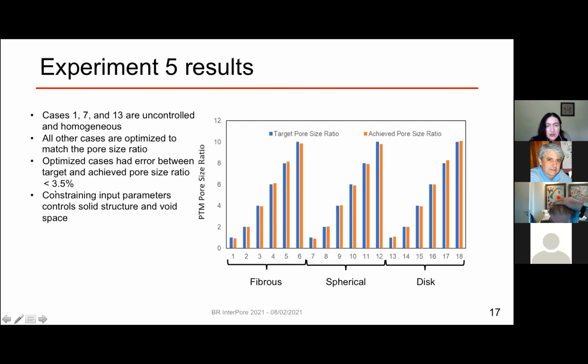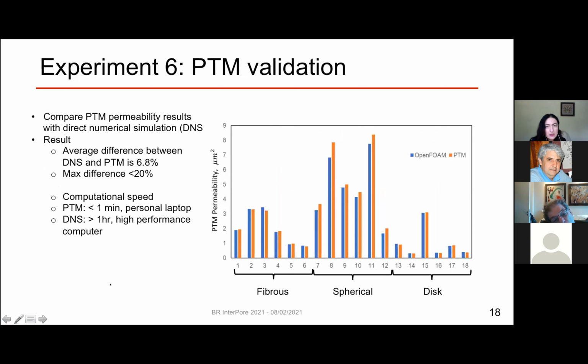So what we find is that constraining input parameters helps us control both the solid structure and the void space, and the error between what we wanted to achieve and what we achieved is under 3.5%. So we're happy with that also. And our sixth and final experiment, we wanted to see how well does the pore topology method perform. That is the one that computes all of these material properties, whether it's porosity, pore sizes, or permeability, compared to direct numerical simulation. And we find that the difference only is under 7%